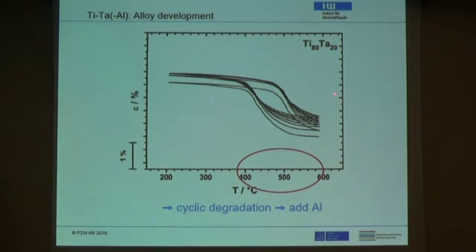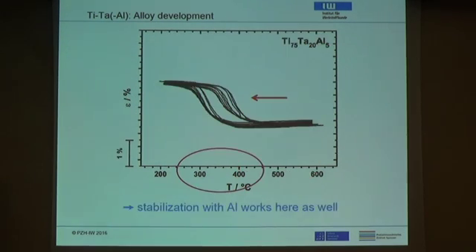Problem, of course, is if you do the cycling, you see that again this material starts to degrade pretty rapidly. But then the solution is pretty obvious. Let's add aluminum. Let's see what's happening. You see this is between 400 and around 500 degrees C. And if you do add aluminum, here this is 5% aluminum, you see that the loops become much more stable and the temperature is shifted a bit to 300 to 400 degrees C, but this is much more than what we needed in the first place. So the stabilization works here as well.